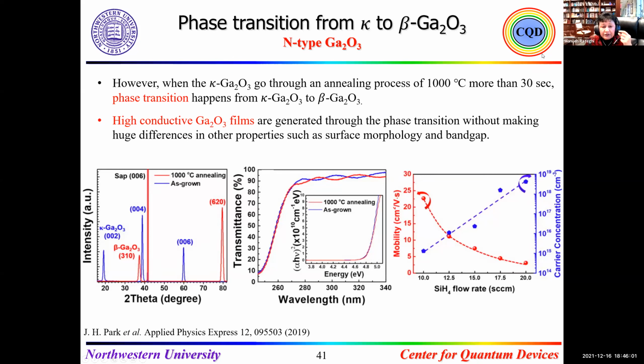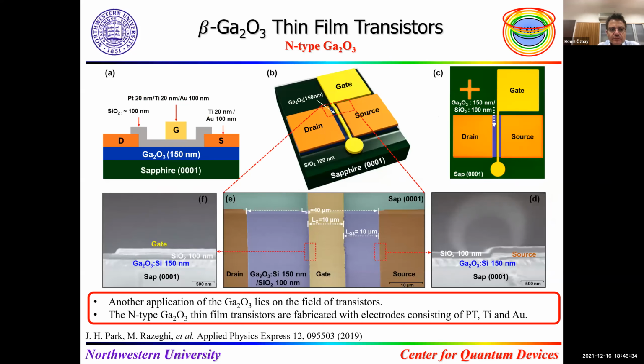Interestingly, we saw that after annealing - here you have the X-ray, the red is after annealing and the blue is as-grown - the symmetry changed to become beta. We confirmed with transmission electron microscopy, yes, it becomes beta. And now, interestingly, it becomes conductive. We can now beautifully measure the conductivity. So we make a transistor.